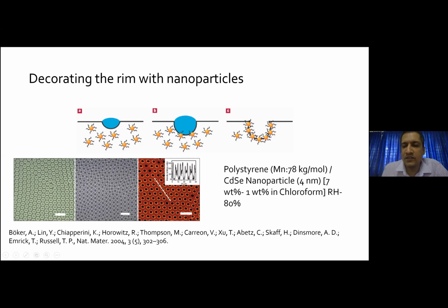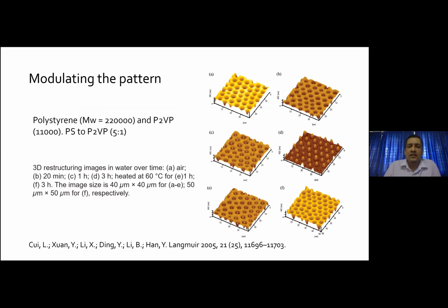So they have achieved this at a particular composition, when you have 7% polystyrene with a molecular weight of 78,000, and then you prepare a 1% solution. Then you prepare the cadmium selenide nanoparticles, which are of 4 nanometer dimension, and you mix them in various ratios, usually 5:1 to 12:1 and so on. At a relative humidity of 80%, they try to generate these kinds of patterns. You can see the fluorescence emanating from the rings, which is indicative of the deposition of these cadmium selenide nanoparticles onto the rim. And this is very interesting work carried out by Han and co-workers.